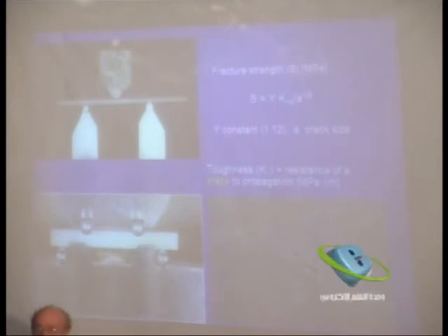the material. This does not happen with metals, because metals usually have plastic deformation before fracture, and so we don't have to worry so much about this; we worry about yield. But with brittle materials, it is the defect size that is important. And this is where you guys have a role. Your adjustments of your materials introduce defects.